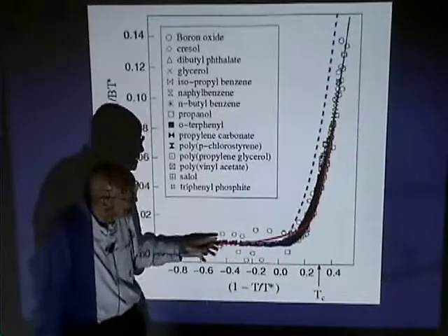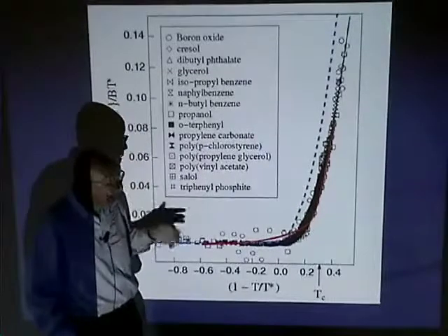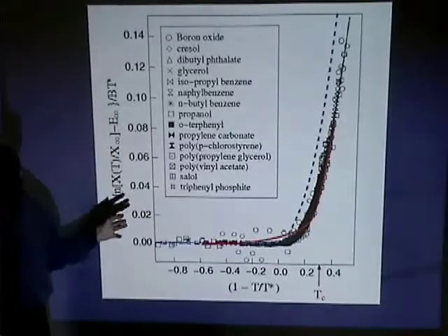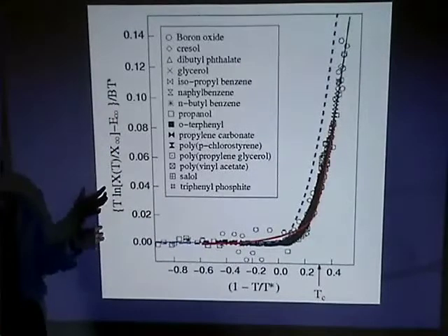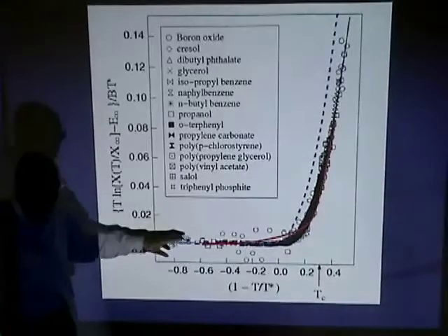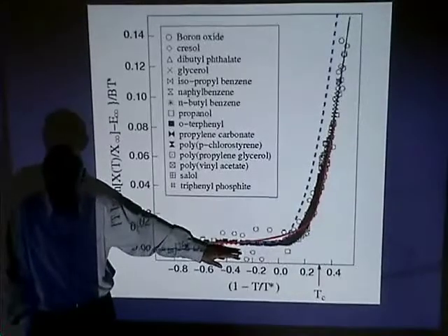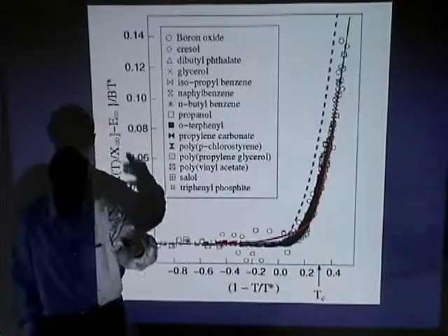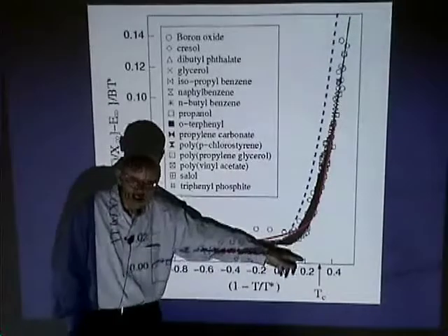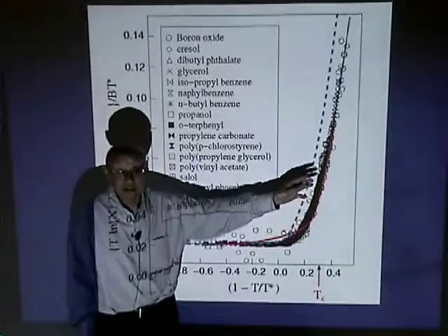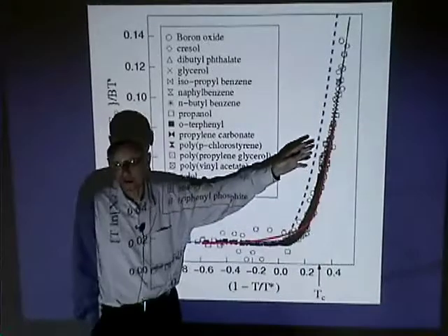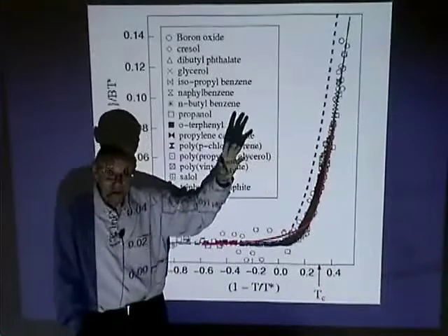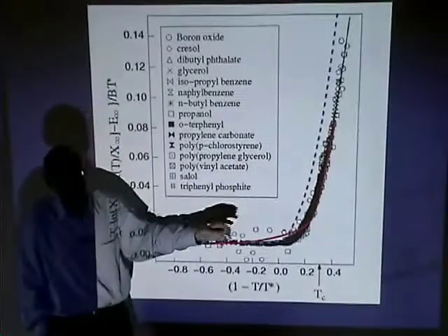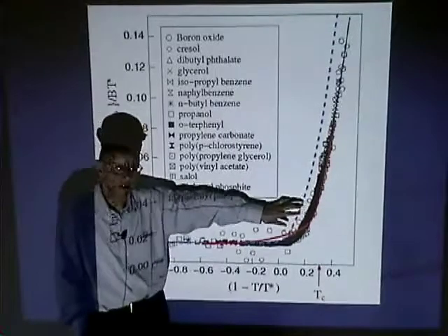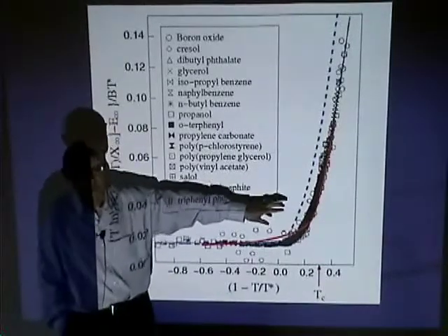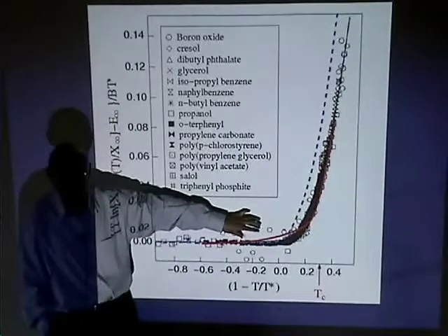There are scatters here, but basically the lesson for us is that if you regard this as a temperature-dependent activation barrier, all the viscosity data tells us is that at high temperature the activation barrier is low, and then at a certain temperature, near TC, the activation energy starts to increase very sharply. That's all you can draw qualitatively from this. Whether the accuracy is good enough, there's lots to discuss, but this is basically our realization now.